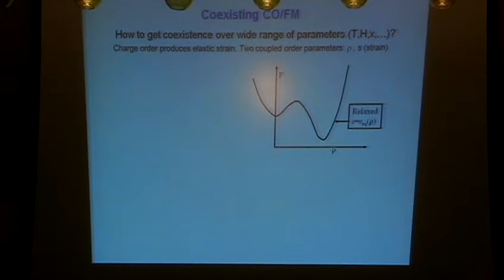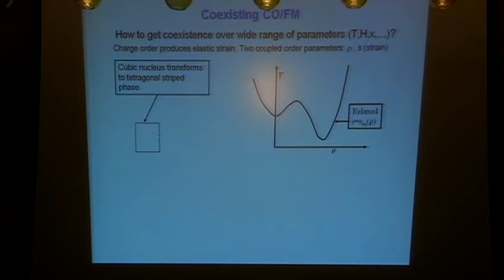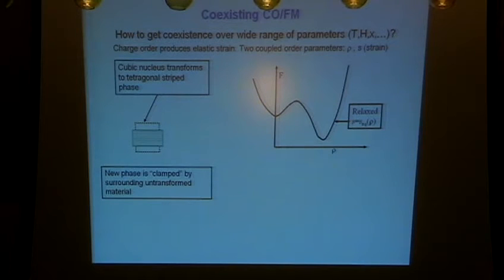Okay. And the point there is that if you have a free energy as a function of some order parameter, which has a couple of minima, so this is going to have a first order transition from this one to that one, and if this is the free energy of the system where the strain has accommodated, this is the ground state. If you clamp the system, however, if you freeze it, as you would be if you took a nucleus inside an otherwise untransformed sample, you have an extra elastic energy cost which would be clamped, which, for example, could bring this minimum above that one. So this nucleus would not be stable and would not grow.